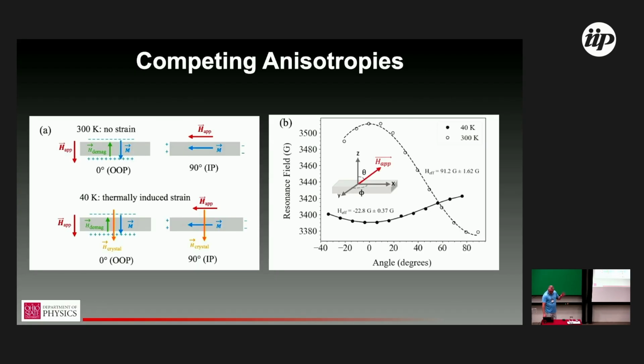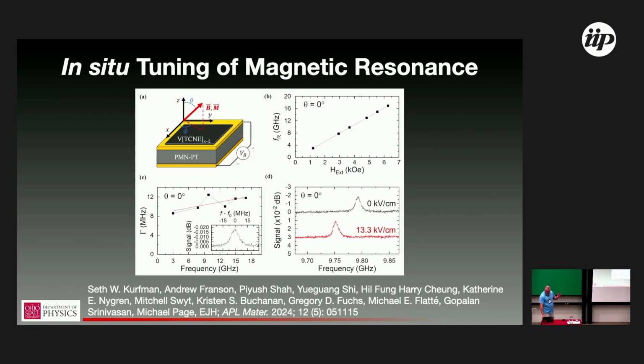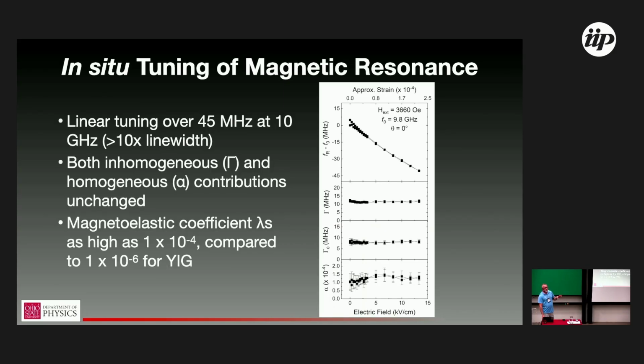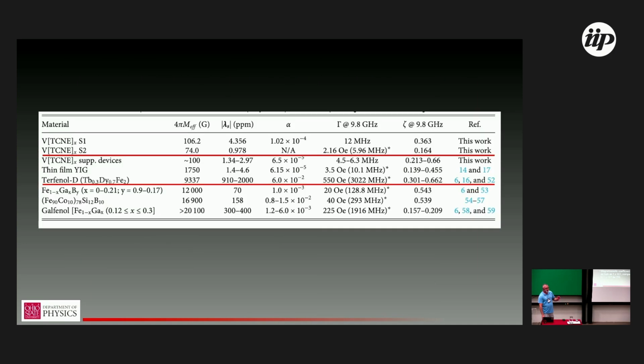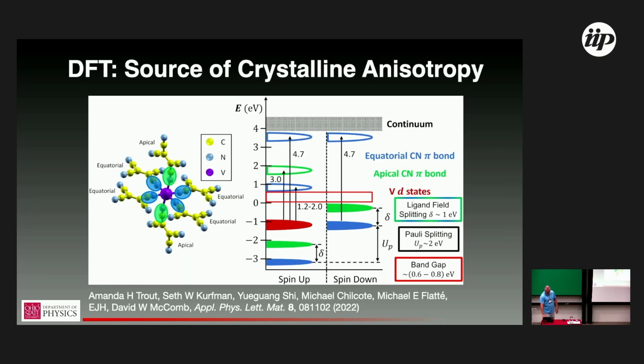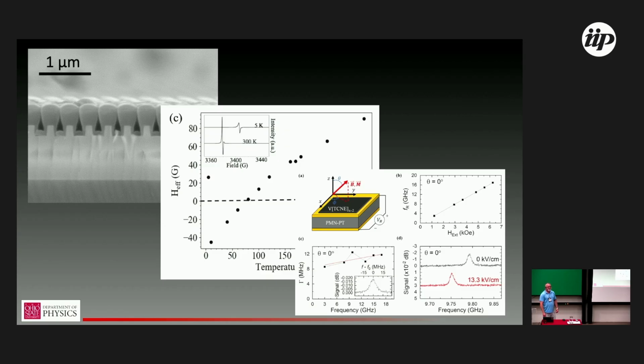Also, just to be a bit pedantic, the variable we have under control is temperature, but I would think of it in terms of strain tuning. It's not inherently a temperature effect that's driving that physics. I think it's the strain between the substrate and the film, which means that it's not the best control parameter. Sample to sample, you can have modest variations in how that works depending on what the interface looks like.